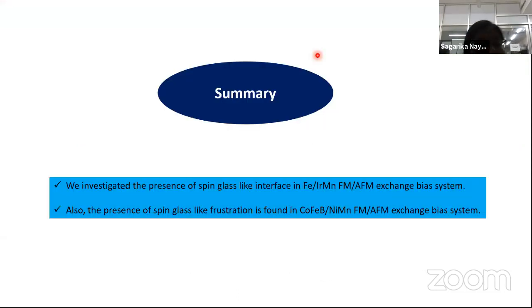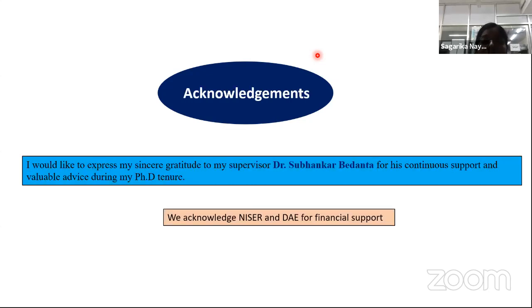So now this is my summary. In the iron iridium manganese system, we found that the interface is spin glass like. Also we found the presence of spin glass like frustration in the cobalt iron boron nickel manganese exchange bias system.